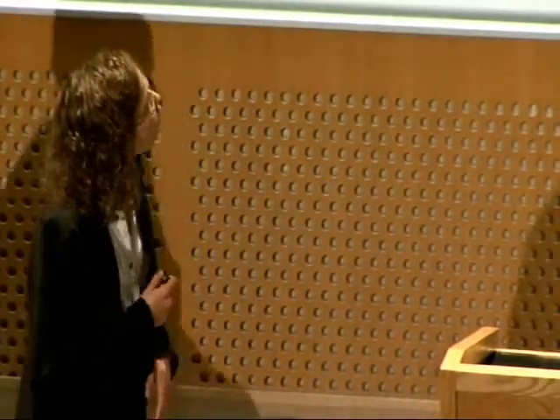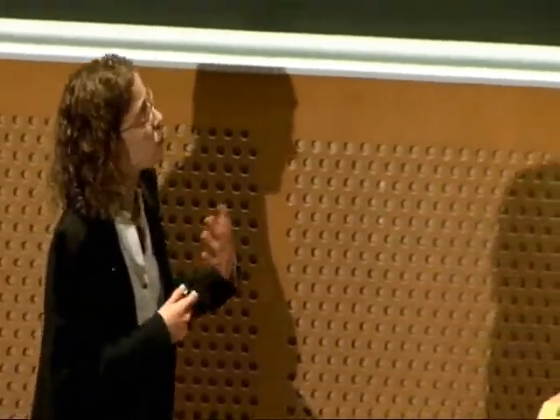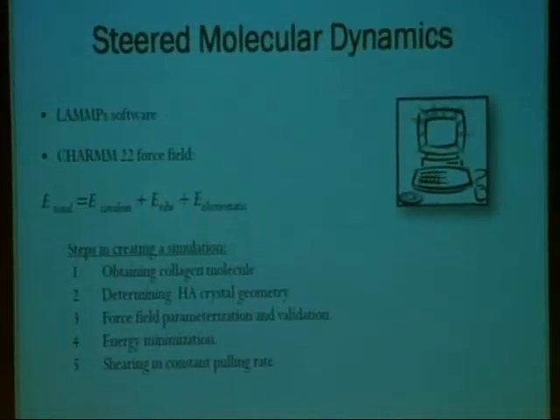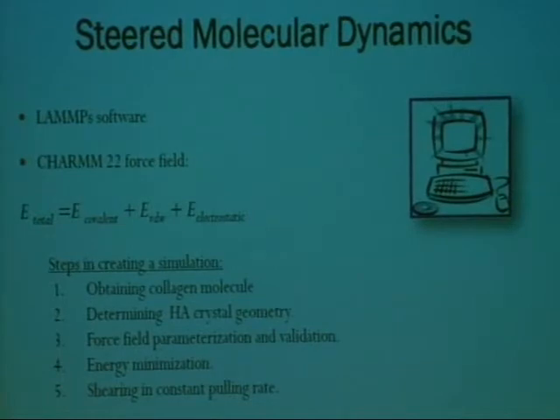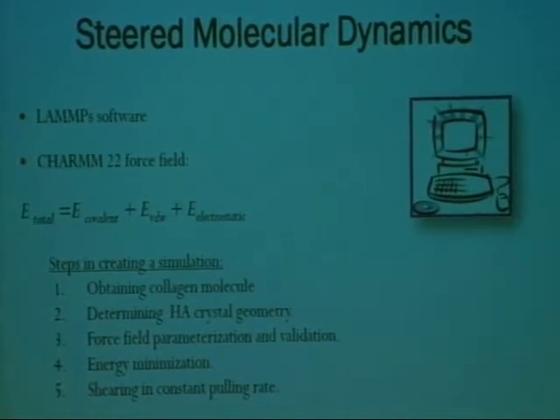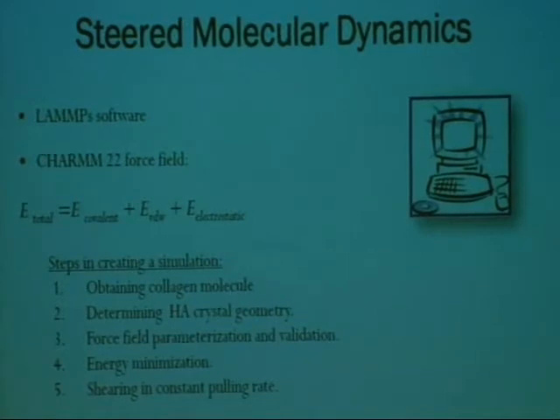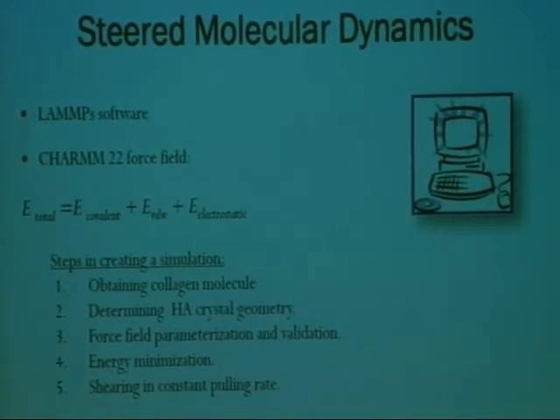After parameterizing it for the hydroxyapatite, we again had to minimize the energy. Then finally, we could shear the collagen across the hydroxyapatite surface. With each time step, after we shear it, we put the system in equilibrium, then shear again — that's how these time steps work, and by the end we have a full simulation of the system.